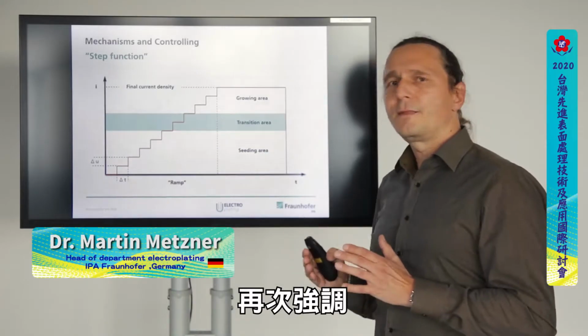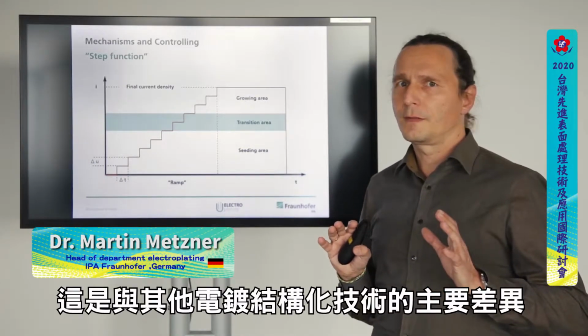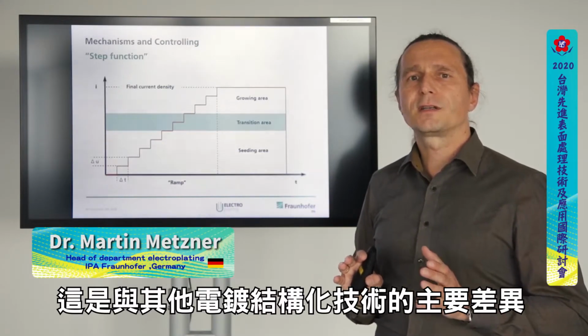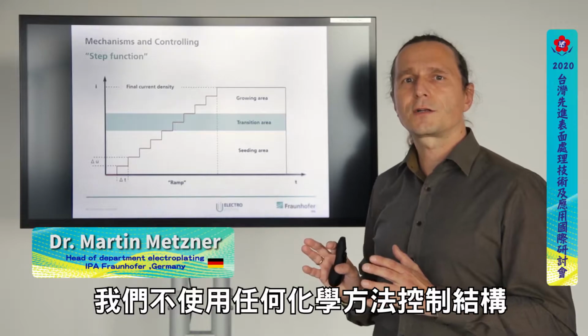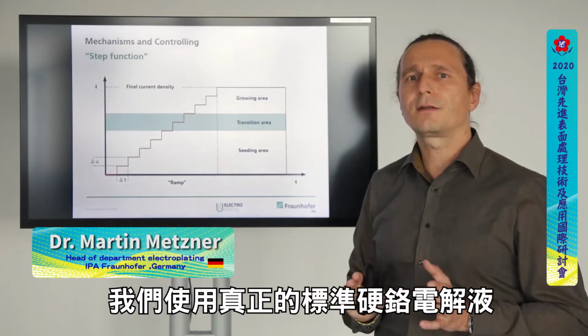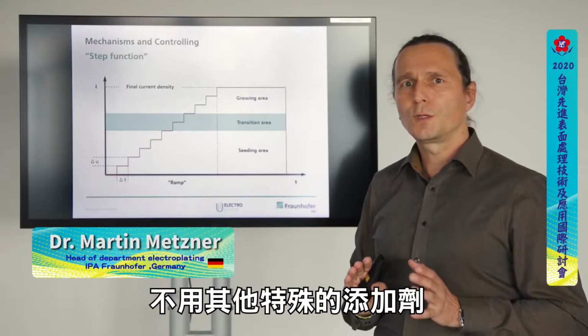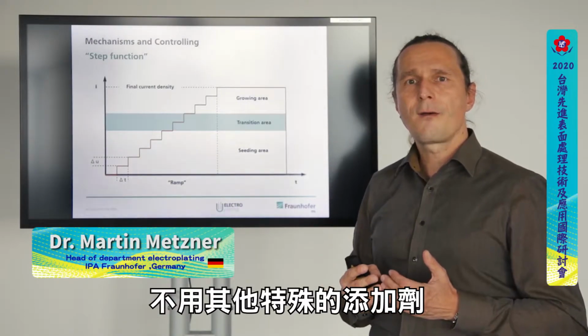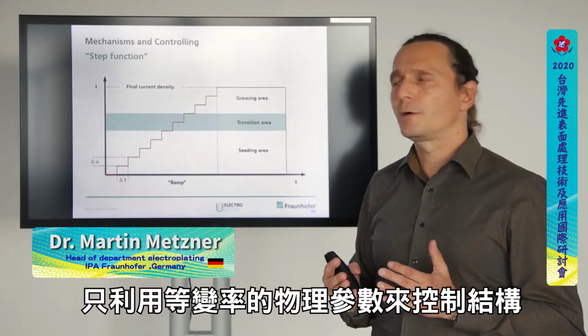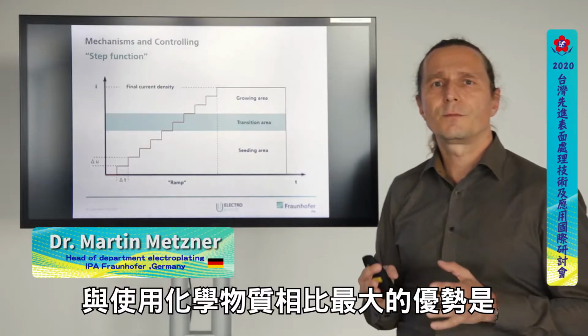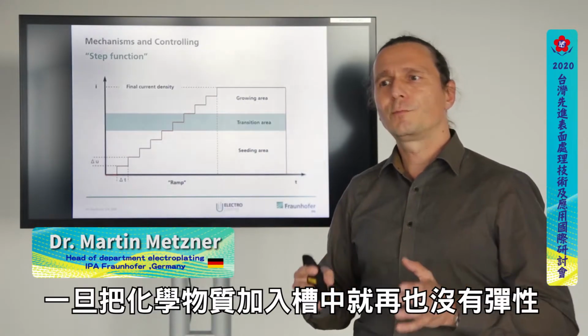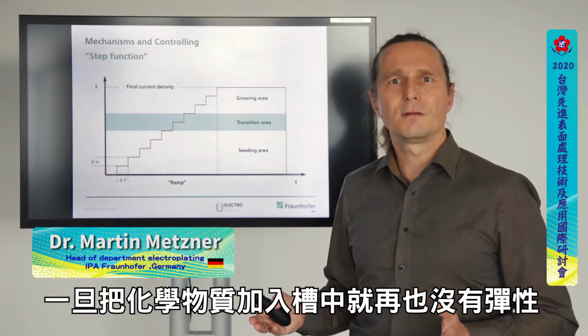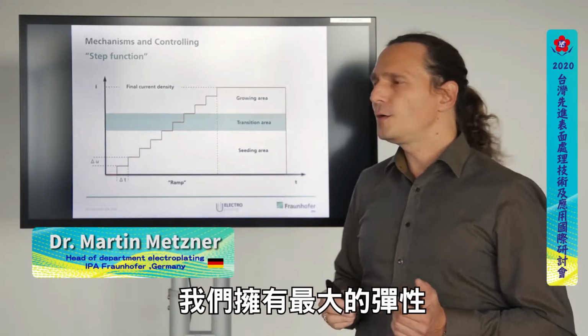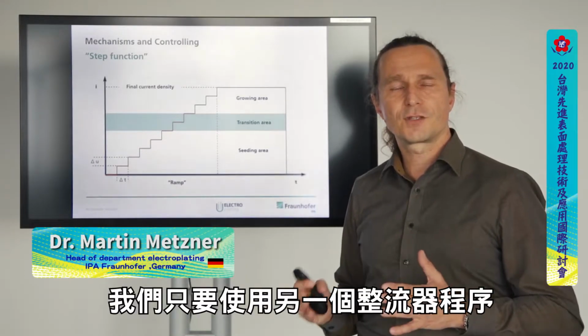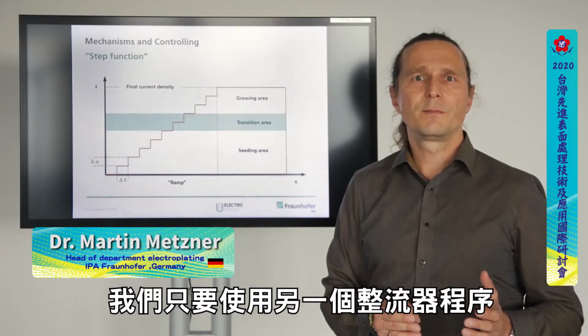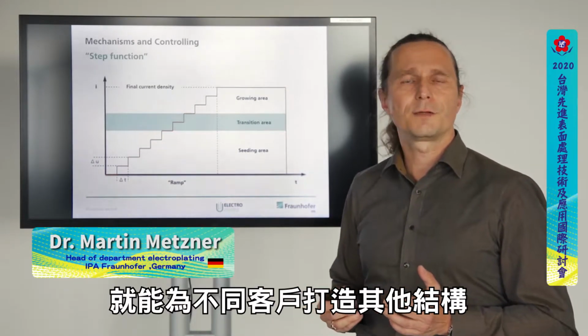To underline this again, this is the main difference to other structuring technologies in electroplating: we do not control the structure by any kind of chemistry. We use a real standard hard chromium electrolyte as you know it, so we do not use any fancy additional agents. We just control the structure by physical parameters in our ramp. The big advantage compared to using chemistry is that when you put chemistry in your tank then you just have it in, so you've got no flexibility anymore. Here we have the maximum flexibility because we just have to use another rectifier program to get into another structure that we want to build up for different customers.